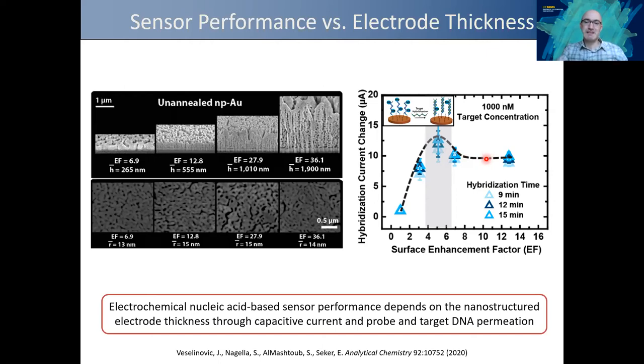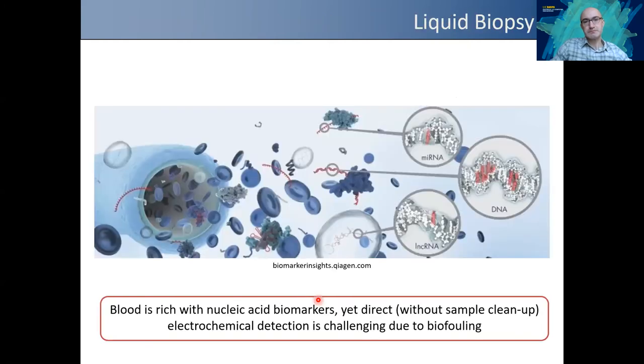And that's where, as we've predicted, the capacitive current and permeation of the nucleic acids become an issue. So we think that we've basically shown that you can tune the morphology and the thickness for optimizing the limit of detection in this case, and also to tune the range of detection with the morphology.